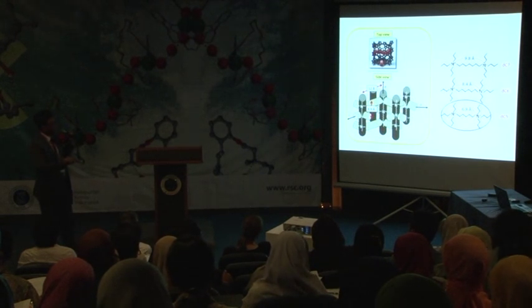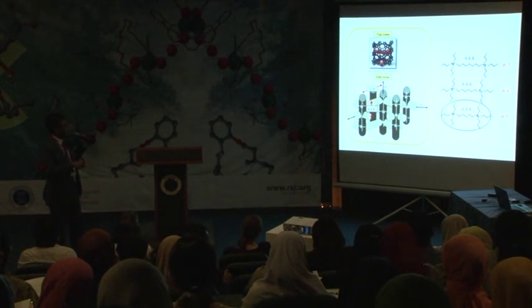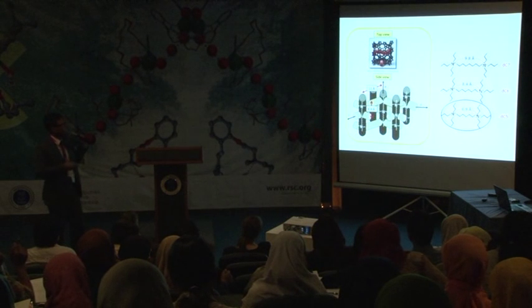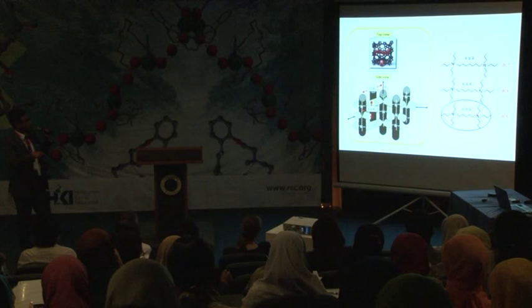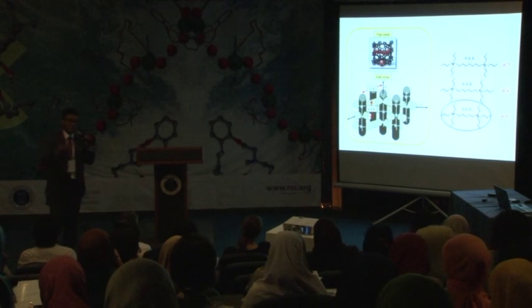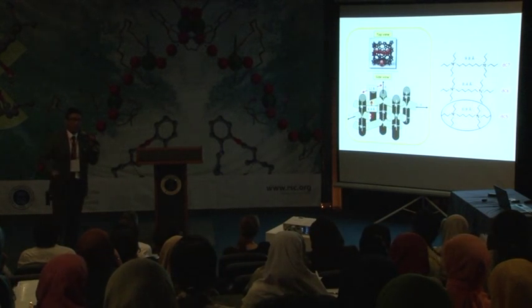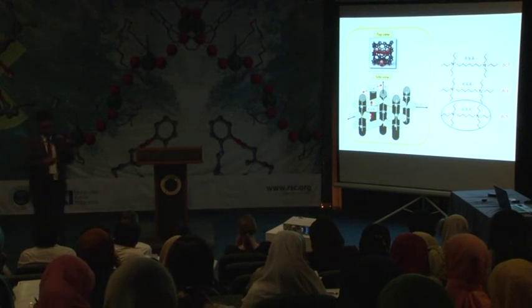So this is what we are using. We were using just C5 spacer between the diammoniums, and probably it will not fit very well in the channel. So it will not go into the second intersections. So probably it stops here. That's what we expect. We just want to inhibit the crystallization of the zeolite, in order to get defect sites, more mesoporosity, something like that.